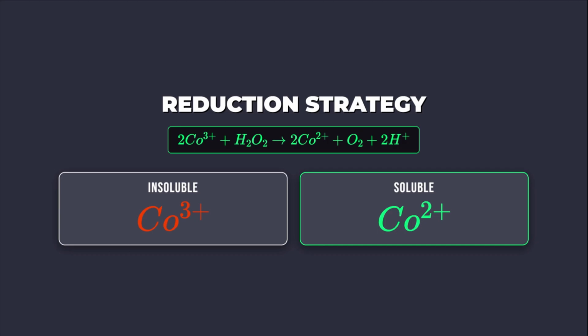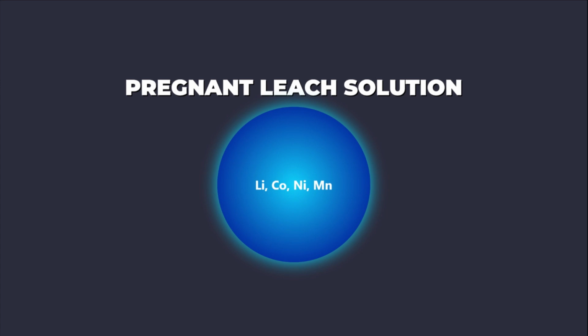Hydrogen peroxide acts as a strong oxidant, but also as a reductant in acidic media, reducing cobalt 3+ to the more soluble cobalt 2+. The reaction yields soluble metal sulfates and water. The use of hydrochloric acid is sometimes preferred because the chloride ion itself can act as a reducing agent, forming chlorine gas, although this requires careful off-gas management due to toxicity. Optimizing the acid concentration and temperature minimizes the leaching time and energy input.